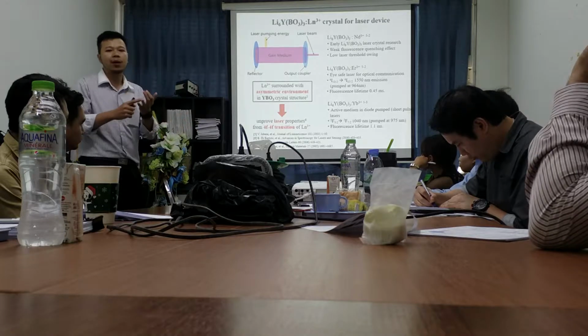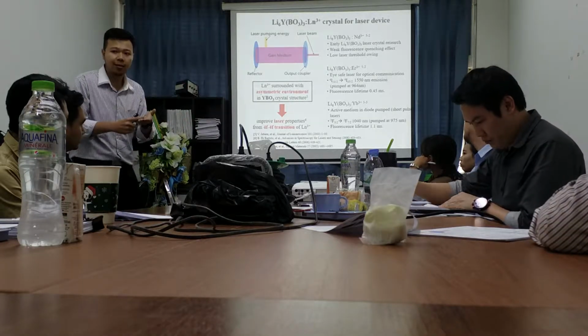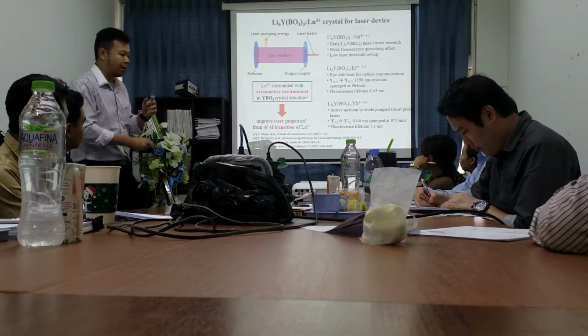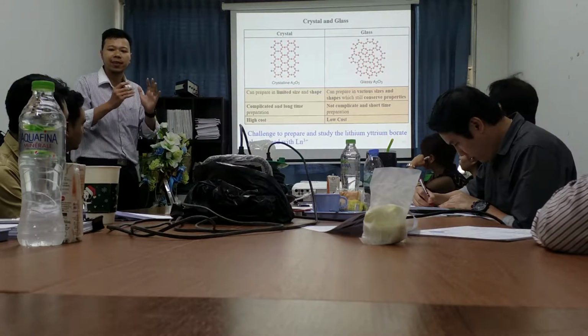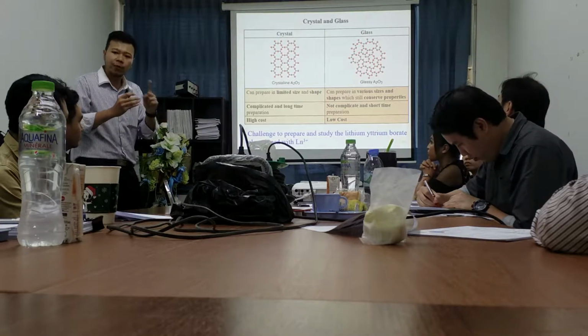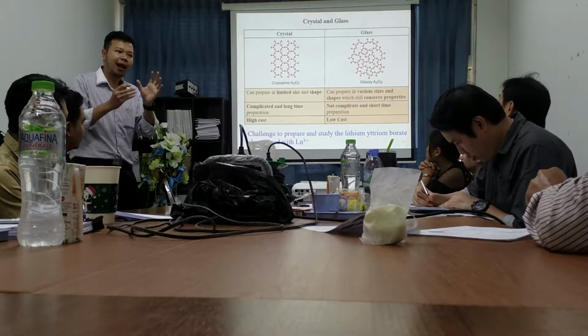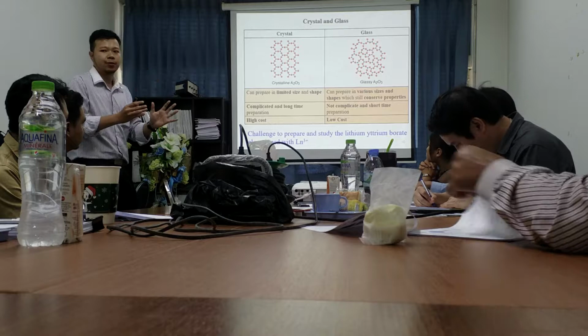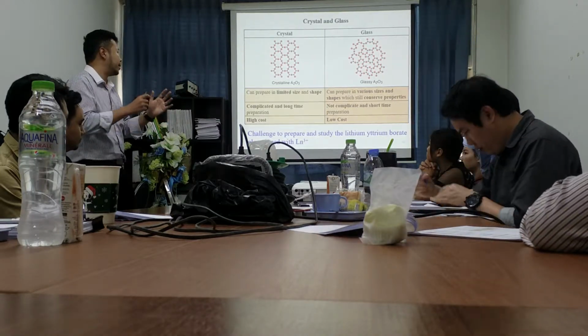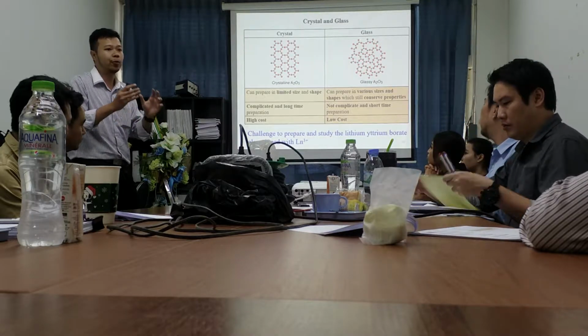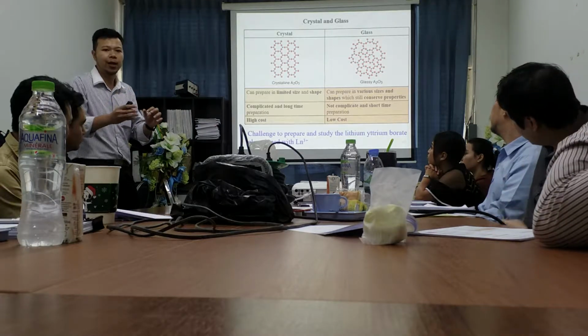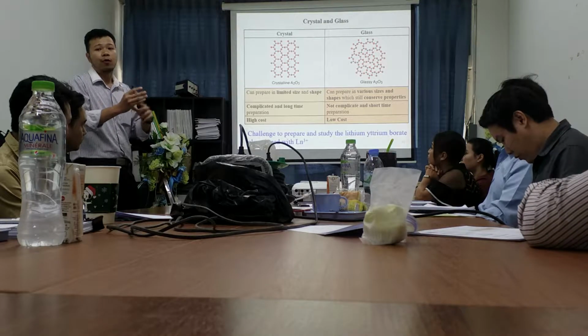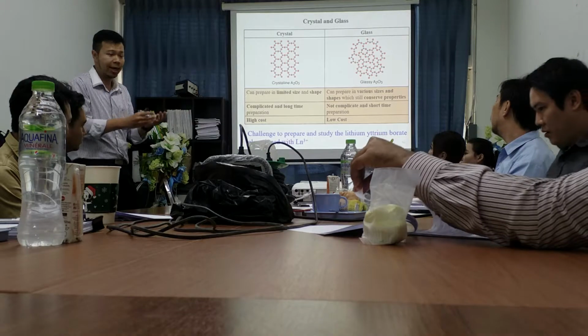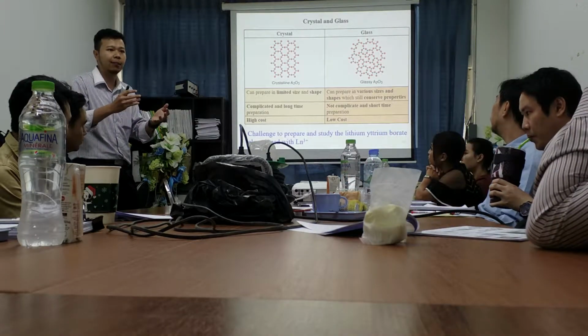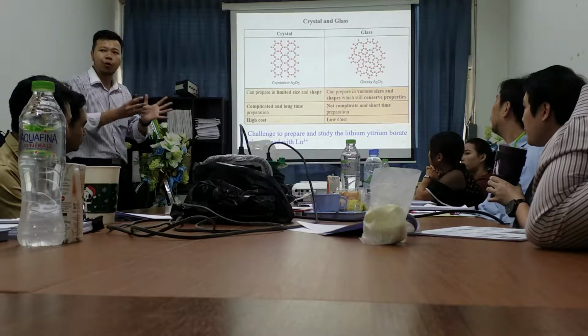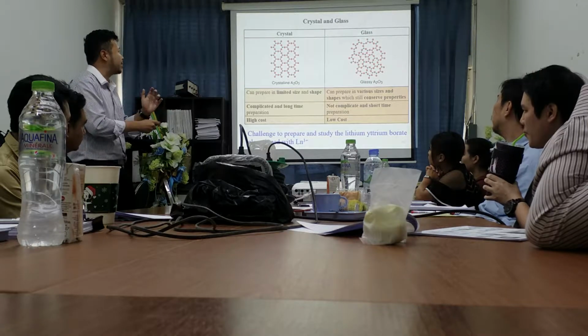As I said, lithium yttrium borate crystal doped with lanthanide ions shows interesting properties, but it is a crystal material, and crystal material still has some disadvantages, such as once you prepare the crystal, you can get just a small piece, and it's hard to control the shape of the crystal. And the process to prepare the crystal is so complicated and can take a long time. This makes the crystal high cost, resulting in a high price for production from crystal. Therefore, we need to find an optional material that can replace the crystal in these devices. Jackpot, we have glass material. Glass material can be prepared in various sizes and shapes in a short time, maybe 1 or 2 days, to get many glass samples. And we can control the shape more easily than crystal. And of course, glass material is cheaper than crystal.